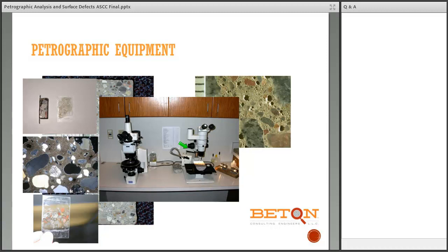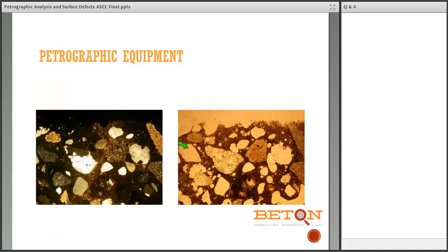My slides are a little jumbled around, I apologize for that. Basically, when you look at a thin section on the polarized light microscope, you have the one on the right here, which is in plain polarized light, and then on the left here we look at it in cross-polarized light, and that tells us a lot more about pastes and aggregates and identifying aggregates and hydration products that we might see, like portlandite or calcium hydroxide.